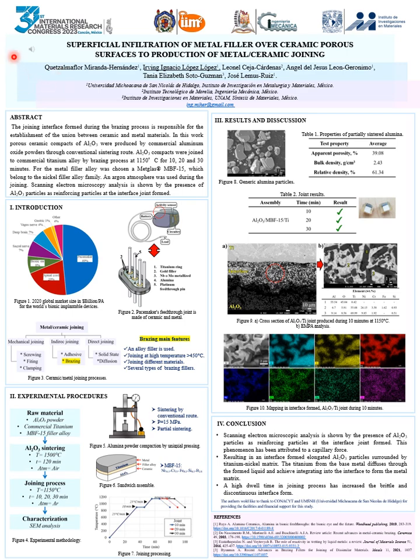Welcome everyone. This work is entitled Superficial Infiltration of Metal Filler over Ceramic Porous Surfaces to Production of Metal-Ceramic Joining. Abstract. In this work, porous ceramic compacts were produced from commercial aluminum oxide powders through a conventional sintering route. Aluminum oxide compacts were joined to commercial titanium alloy by a brazing process at 1150 degrees Celsius for 10, 20 and 30 minutes.